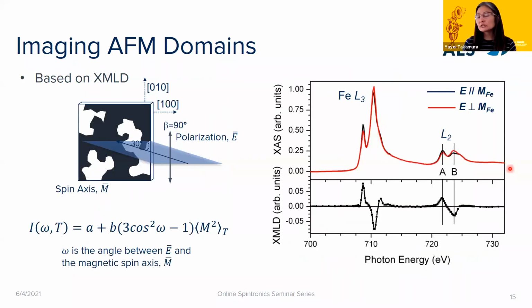And so then if we want to look at the imaging that we can do for antiferromagnetic domains, this again is using linear polarized X-rays. For example, if I come in with linear polarized X-rays which are vertical, right, and let's say I had antiferromagnetic domains here, where black versus white are different antiferromagnetic domains, then I'll find that the E vector is either parallel or perpendicular to the antiferromagnetic spin axis within these two domains. I'm going to get this kind of local X-ray absorption spectra.